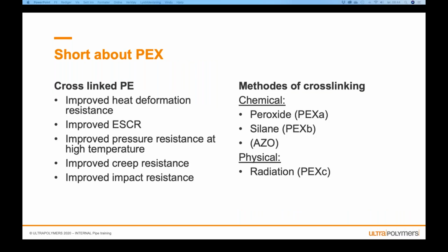So also a bit short about crosslink. Why did I use crosslink material? It has improved heat deformation resistance, improved stress crack resistance, and improved pressure resistance at very high temperature, improved creep resistance, and improved impact resistance. What you should know about cross-linked polyethylene material is that it's not mechanically recyclable. It might be that we can chemically recycle it in the future, but that's a bit way ahead, but hopefully we can manage that.